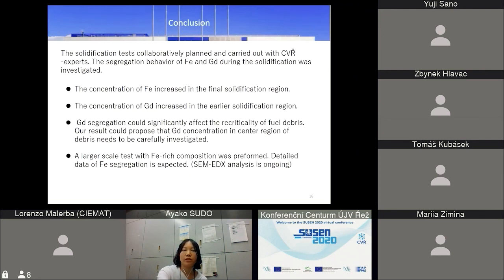Okay, this is the conclusion of this presentation. The solidification test was collaboratively planned and carried out with several experts. The segregation behavior of iron and gadolinium during solidification was investigated. The concentration of Fe increased in the final solidification region. On the other hand, the concentration of gadolinium increased in the early solidification region. Gadolinium segregation could significantly affect the criticality of fuel debris. Our result suggests that gadolinium concentration in the center region of debris needs to be carefully investigated.